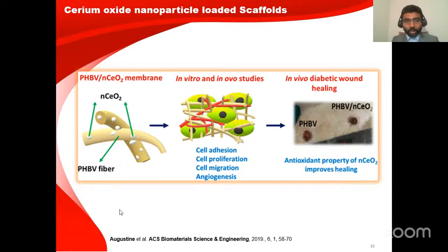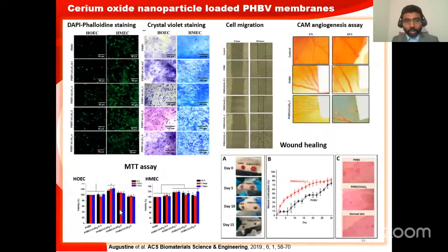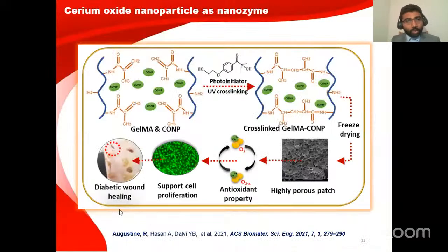healing activities. You can see here, when we conducted cell cultures, the cells were able to attach very well on the scaffolds and showed higher cell migration when the cerium oxide was present, and also higher wound healing. Also, we used such nanomaterials, cerium oxide nanoparticles as nanoenzymes, in gelatin methacrylate scaffold. GelMA means gelatin methacrylate. Then using a photo initiator, we cross-linked GelMA containing cerium oxide nanoparticles to make a hydrogel. Then after freeze drying, we got highly porous scaffolds.